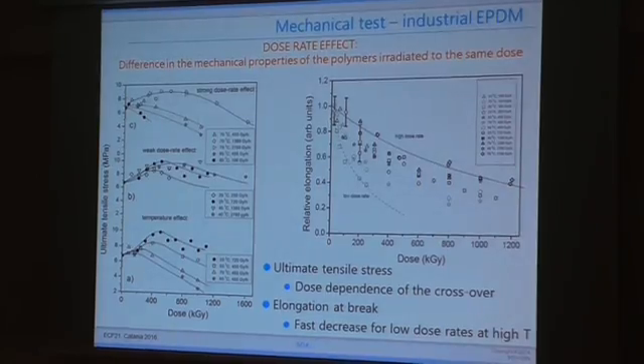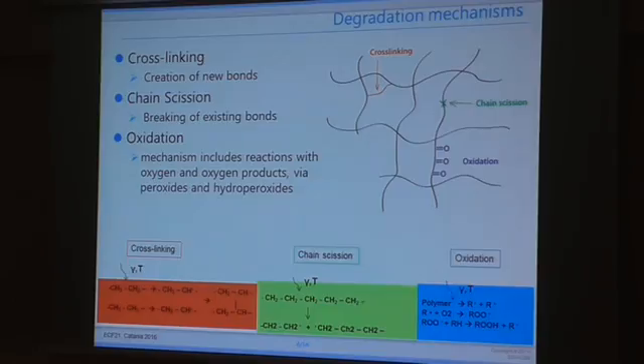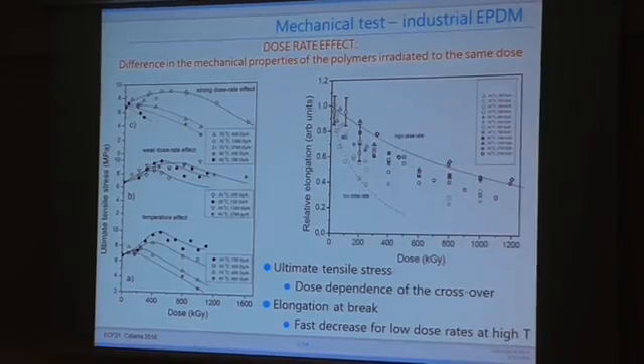And now, in practice, we see the dose rate effect as a difference in mechanical properties for polymers that are aged up to the same dose. So, for example, if we check the ultimate tensile stress, we can observe that it increases and decreases. It increases if we have cross-linking, so creation of new bonds, as the dominant mechanism, and it decreases if we have chain scission, breaking of bonds, as the dominant mechanism. And we can observe this maximum, which is the crossover from cross-linking to chain scission dominance.